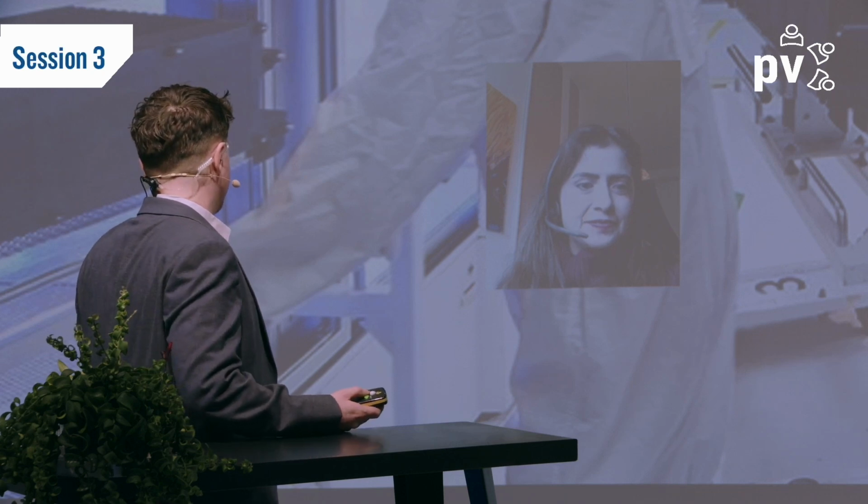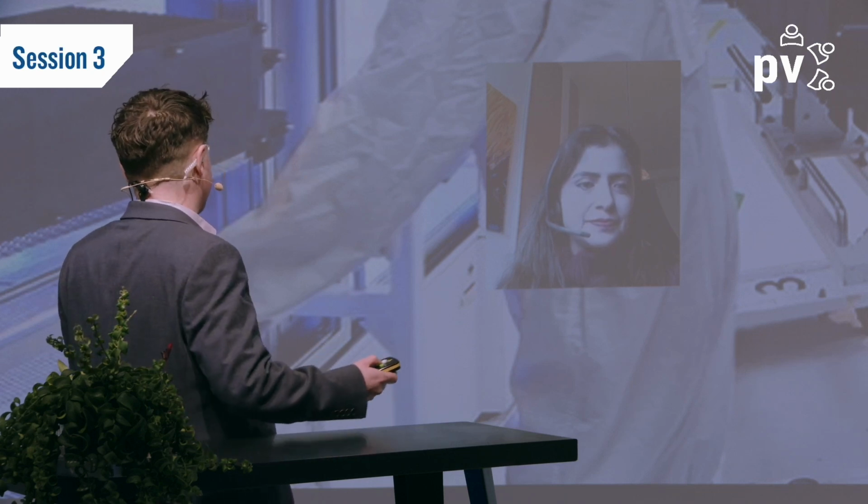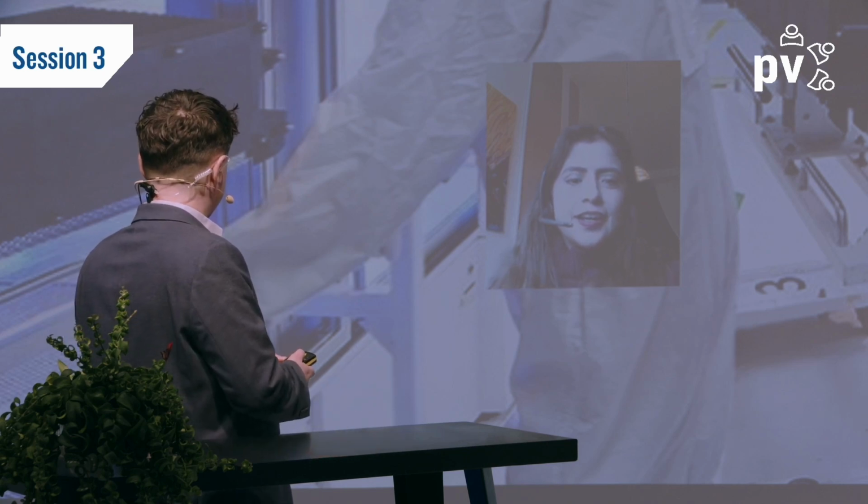And in 2024, we saw a few significant improvements with TOPCon technology. What do you see as the most important so far? Well, I would say that there are things that we don't see, especially in this industry. The final result is the module, but at the wafer level, for example, especially the rise of N-type silicon has made a lot of improvement in the wafer quality. We have tighter control of the oxygen content, for example. We have shifted towards using ultra high purity silicon, so this is going up to 9N, which means 99.9999999% of purity. This is compared to levels of 8N or something different that we used in the past.